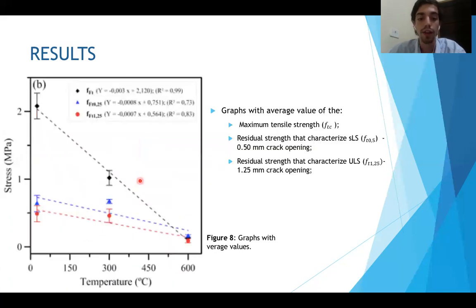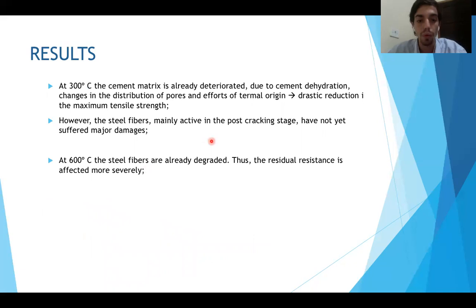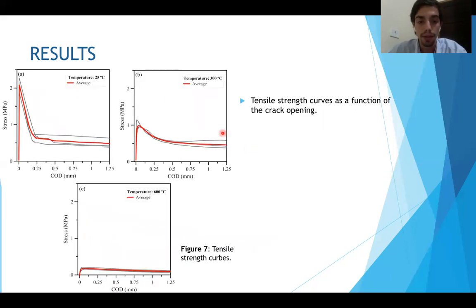The average values of these curves are plotted here. Peak resistance at break in black, residual tensile strength in SLS in blue, and strength in ULS in red. A reduction in resistance is observed with an increase in temperature. Then, what is noted is that at 300 Celsius degrees, the peak resistance has a big reduction compared to the ambient temperature. But the residual strength does not suffer a big reduction.